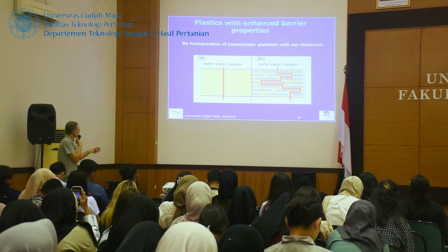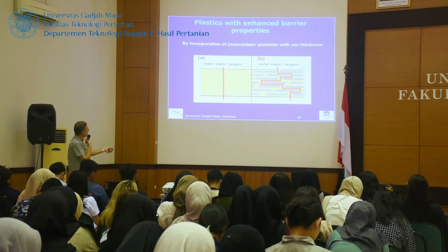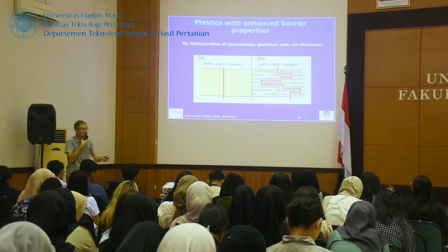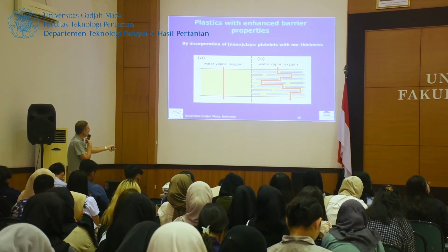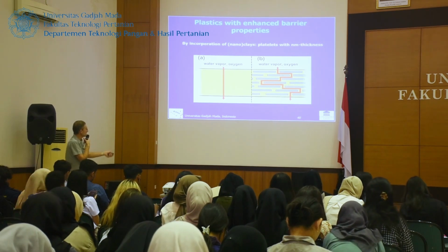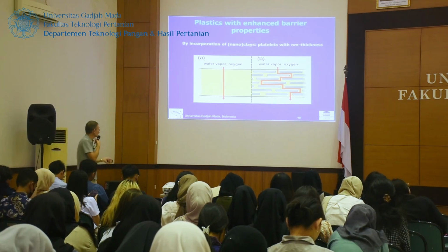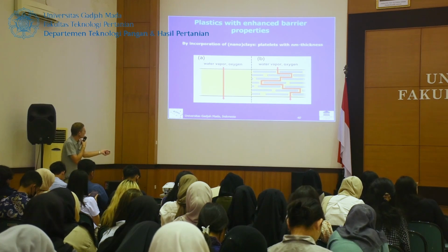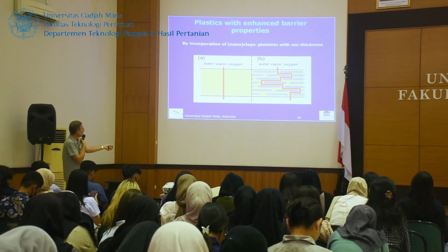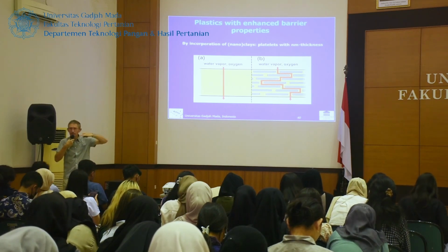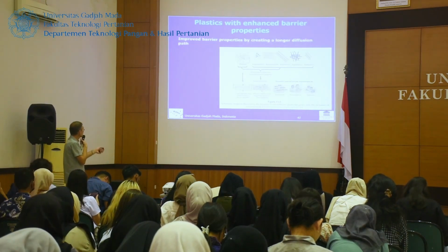The main principle of having nanoparticles present in your polymer material is that diffusion cannot follow the shortest distance, but your diffusing oxygen must move around your small nanoparticles that are present, and as such create a much longer path, which largely slows down diffusion. You see already here that, quite frequently, non-spherical particles are used. Nanoclays are typically used, and clays in this typical flake-like geometry is what you see here.